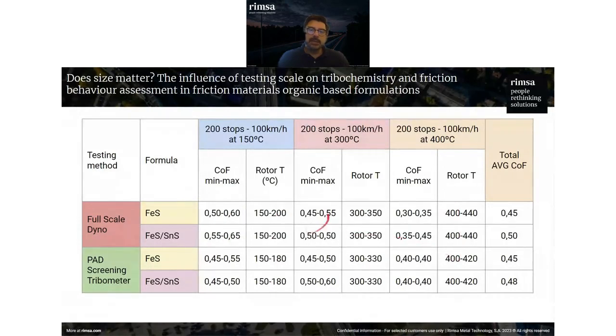You can see in the full-scale dyno, this is the rotor temperature, the temperature on the counterpart, on the cast iron rotor surface. So we have achieved slightly different coefficients of friction and slightly different temperatures, but they are close enough to be considered in the same range. So for the total average coefficient of friction, we may see the same trend. The average coefficient of friction increases a little bit when using the composite sulfide compared with the iron sulfide, and this is the same case both in the full-scale dyno and the pad screening tribometer.